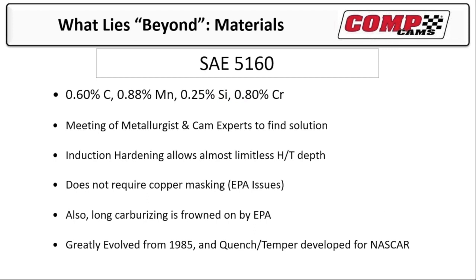5160. 5150 and 5160 both started when both the aftermarket and OEs all went this way at the same time. There were a lot of metallurgists, a lot of people sitting around tables going, if we could make the best possible camshaft, what material will we use? And somewhat surprising, this is sort of what came out of it. What makes 5160 so good is that induction hardening lets you really tune in the heat treat. You can make it deeper or shallower.